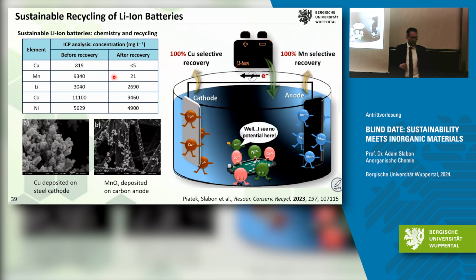So what's happening here is you can compare it to playing poker on a round table. When we come from the outside with two electrodes, copper goes to the left, manganese to the right side, and these other ions continue playing because they see no potential in here. Then you can separate them in the next step, and recover the whole solution, basically.